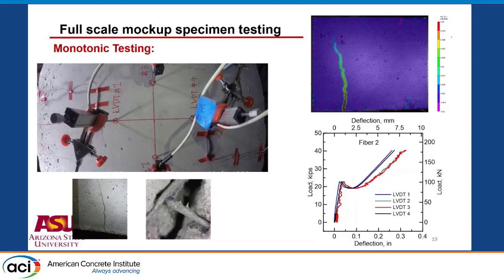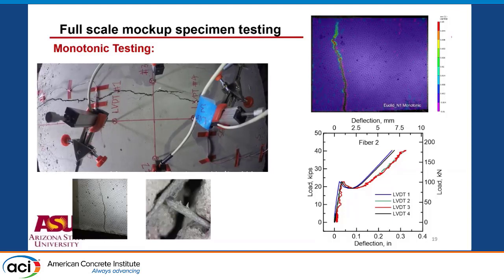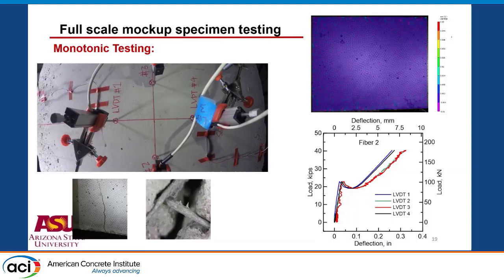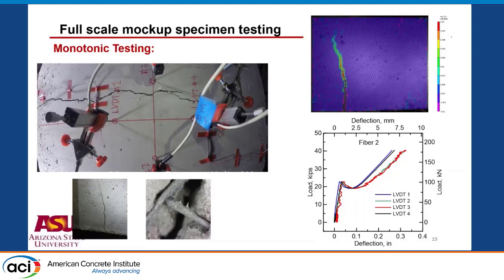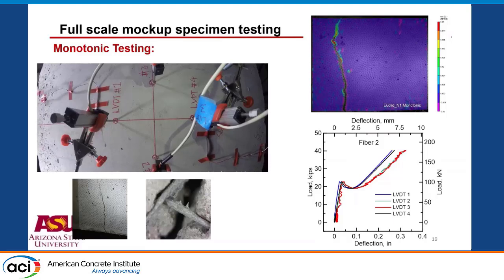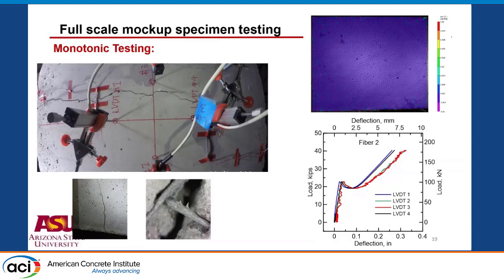Fiber provides a certain level of stiffness, not as much as the stiffness of the steel, but then it deforms. How much does it deflect at the end? When you go to about 40,000 pounds, which is about 6 times the service load capacity, 0.3-inch deflection. That's what you would get, which is reasonable as far as the train ride, with people maybe not detecting that in the process. So, let me go to the next. So this is the type of crack that we see.